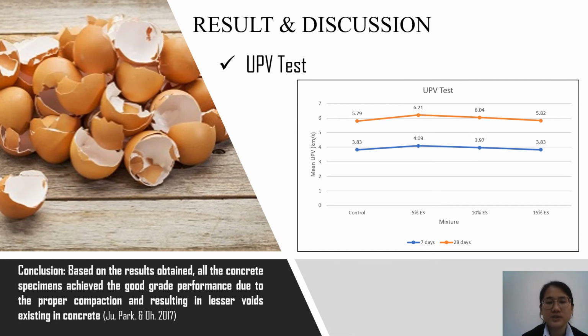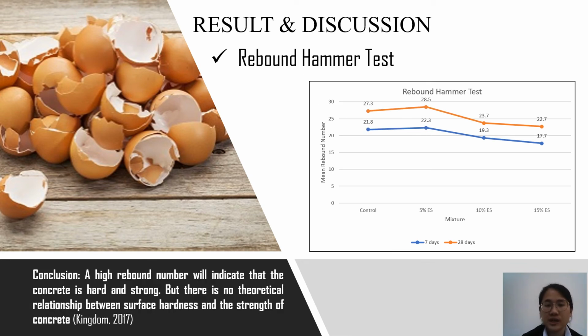Thirdly, the ultrasonic pulse velocity test, known as the UPV test, is conducted in this research to evaluate the homogeneity performance of concrete. Based on the result obtained, all the concrete specimens achieved good grade performance due to the proper compaction, resulting in fewer voids existing in concrete. Fourthly, the rebound hammer test is conducted in this research to determine the surface strength of the concrete. Based on the result obtained, we can conclude that a high rebound number indicates the concrete is hard and strong. But there is no theoretical relationship between surface strength and compressive strength of concrete, according to the research done by Kingdom 2017.